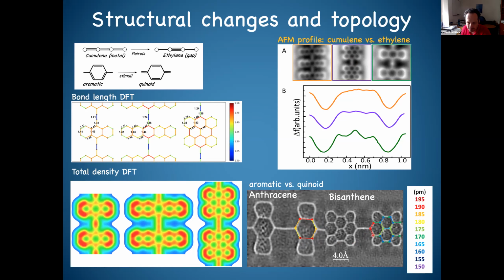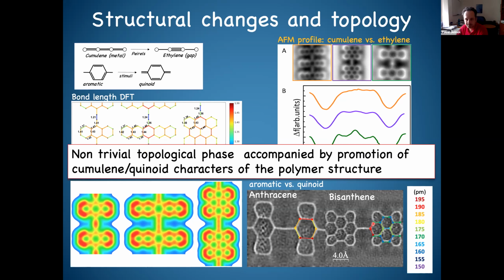So, especially this bond, we can see that in the case of anthracene it becomes shorter, and in the case of bisanthene it gets larger. So again, we have some indication that this topological phase is connected to the p-conjugation. So we can talk about a concept which comes from condensed matter, the topological phase. It can be adopted to chemistry, to these p resonances of p-conjugation.